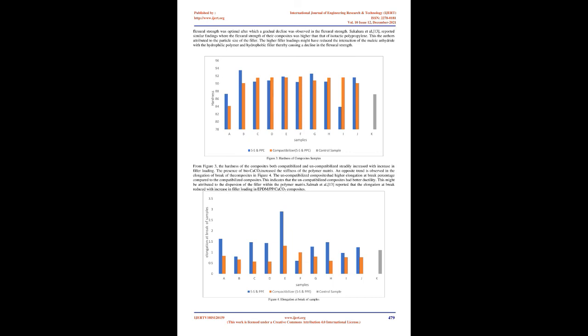At 30% SS loading, composites without maleic anhydride had better flexural strength, 25.3 MPa. Increasing the filler loading above 30%, the flexural strength of the composites decreased. PP/SS/MA composites had low flexural strength at lower filler loading, but at 60% filler loading, the flexural strength was optimal, after which a gradual decline was observed in the flexural strength.